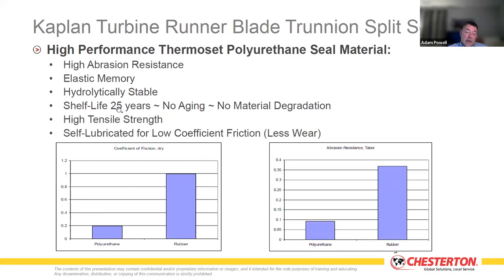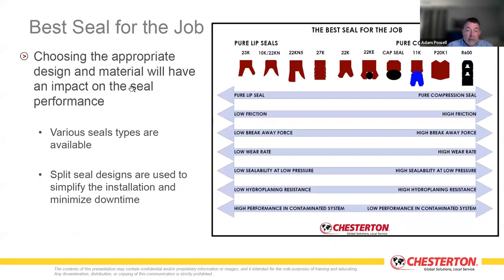So in a turbine where you're looking to get upwards of 10 years between maintenance, 7, 8, 9 years between maintenance periods, having this shelf life and being able to store a seal at a facility without the concern of keeping an eye on lot date codes is very powerful. So we have 25 years, no aging, no material degradation, very high tensile strength. You can stretch this, not that this really will be in a tensile loading environment, but it has high tensile strength, and it's self-lubricated, so it has a very low coefficient of friction, much lower than rubbers and other compounds. Best seal for the job.